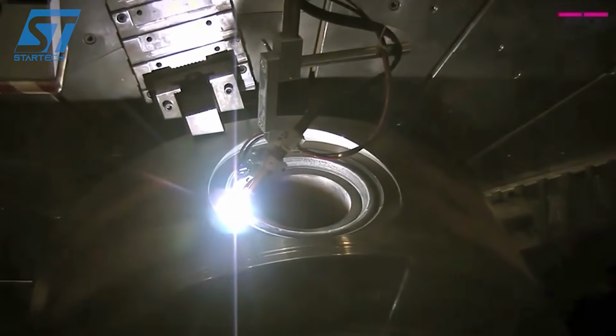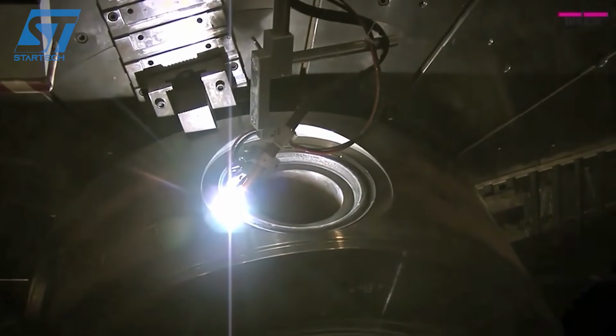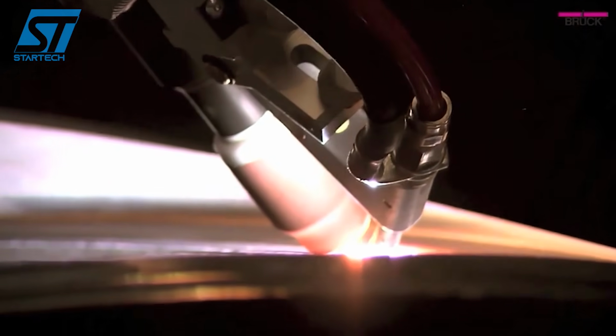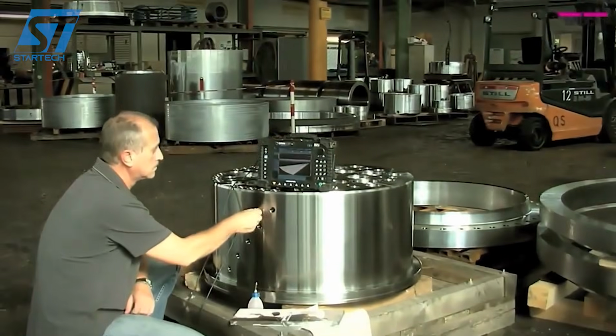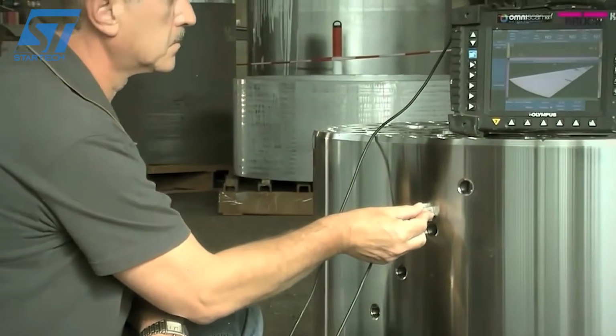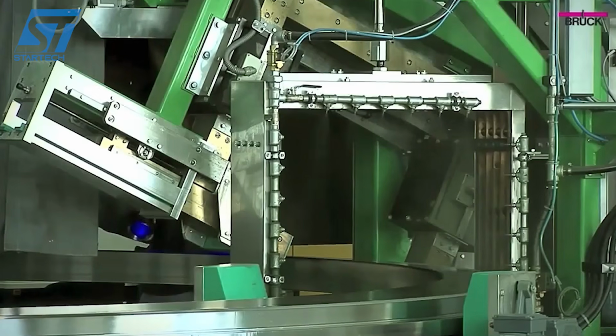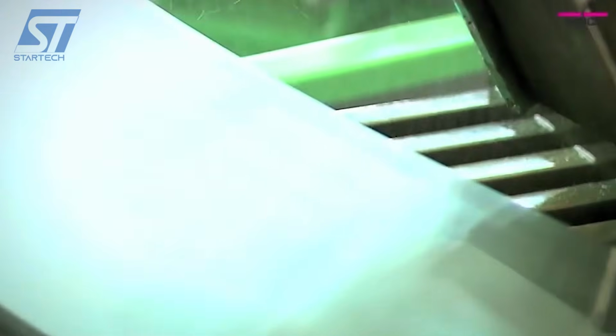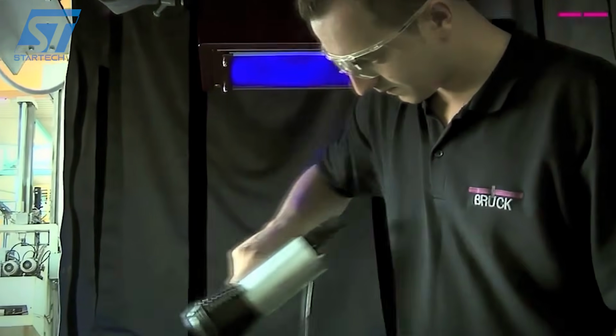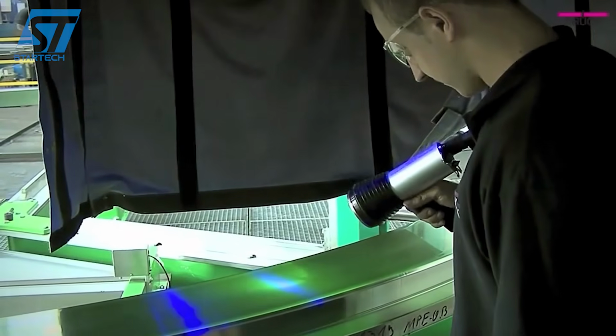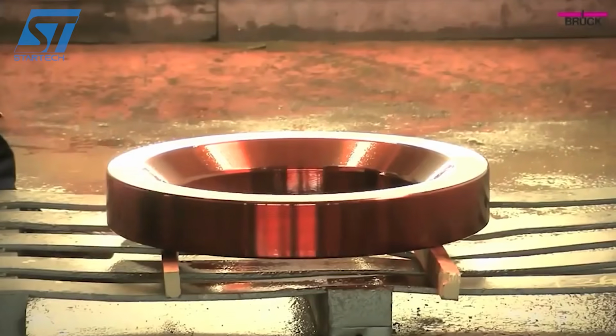It handles rotational stress, temperature cycling, and fatigue loading far better. After rolling, the ring is transferred to a calibration press for final sizing, then moved to a controlled cooling station to prevent stress cracking. The finished rings from Bruck serve industries where failure is simply not an option. Aerospace, power generation, pressure vessels, and heavy machinery. Each ring is inspected ultrasonically and dimensionally before leaving the floor.